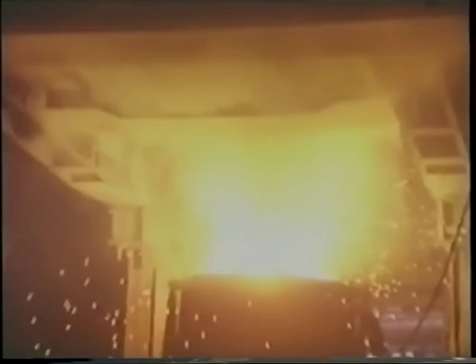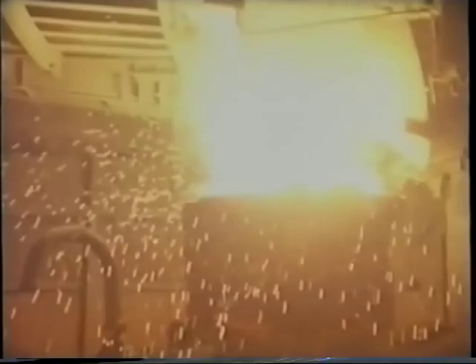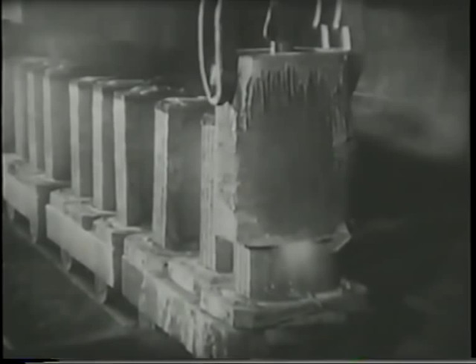In 1960, the UK's first top-blown converter was commissioned, followed by two others. These three 36-ton capacity vessels were filled with molten iron through which oxygen was blown at supersonic speeds by means of a water-cooled lance. Finished steel, regardless of by which method it had been produced, was then cast into 13-ton ingot molds.